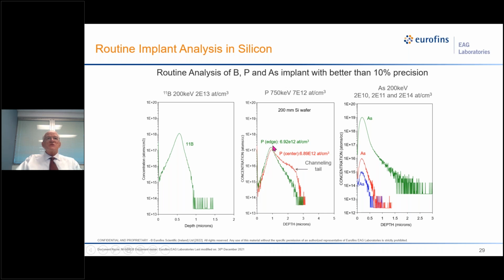The center one shows the difference if you implant the phosphorus, in this case, along a channeling direction, so the phosphorus atoms kind of sneak along in between the rows of silicon atoms. You can get an anomalously deep penetration. The SIMS can see that.